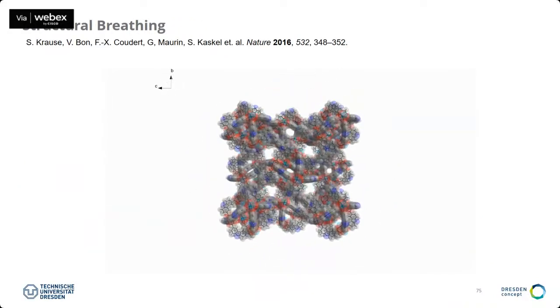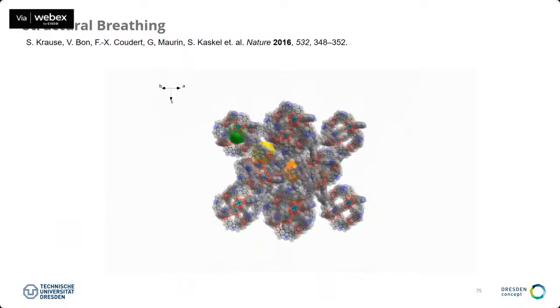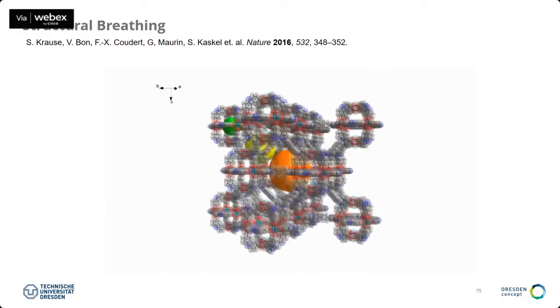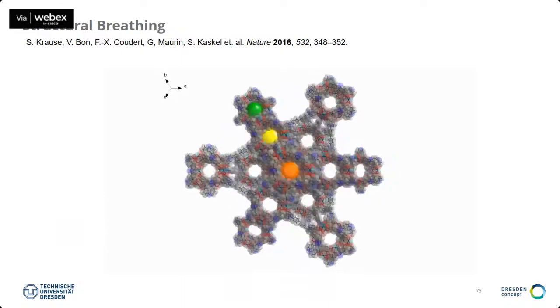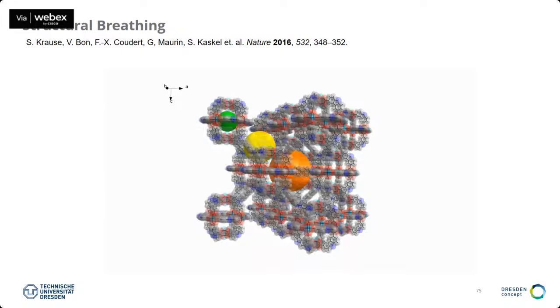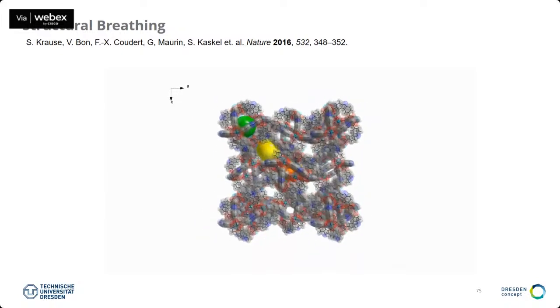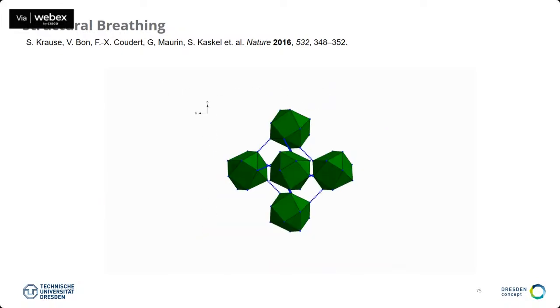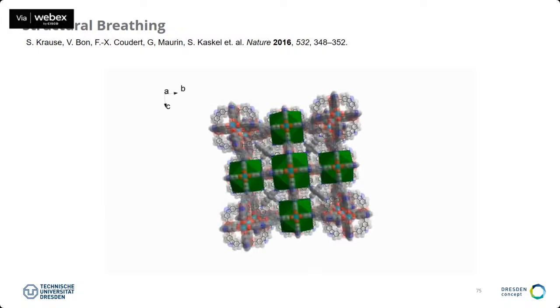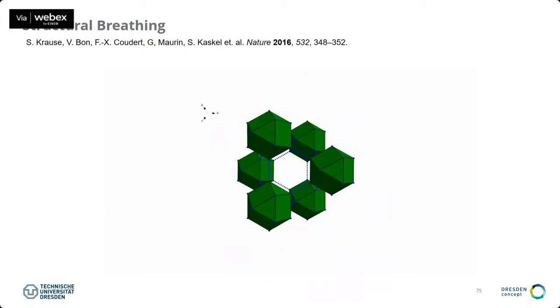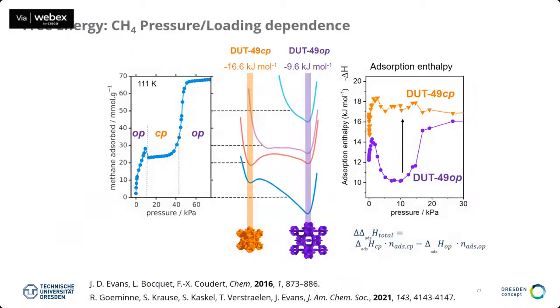Here you can see also this kind of buckling and the transformation of the pores. This is the inner pore of 2.4 nanometer, which is then contracting into a 1 nanometer size pore, and the other pores are also contracting. Only the op pore is not contracting very much. So this is a self-contracting structure, and you're wondering why this is the case. Why should you contract yourself? Why should I pull myself together? But the reason is purely energetic.